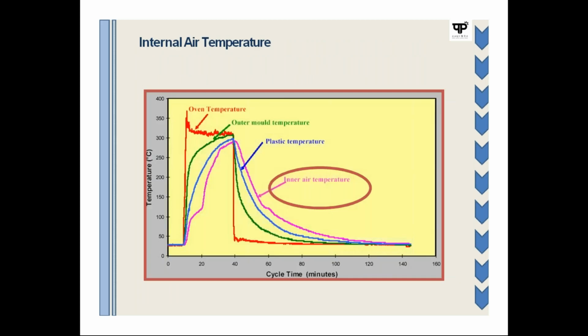Now, another important part is the internal air temperature. You can see the outer oven temperature, the outer mold temperature, the plastic temperature, and the inner air temperature. These temperatures are very important to get good quality of material, especially because the fusion of the particles is going to depend on this internal air temperature.